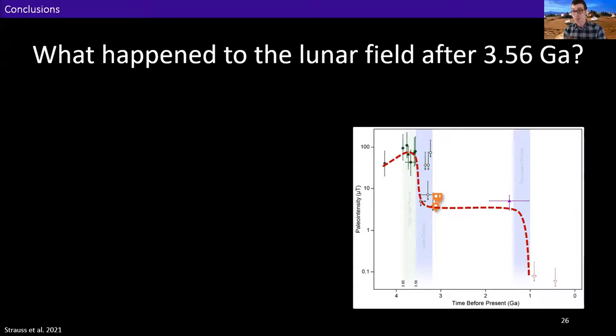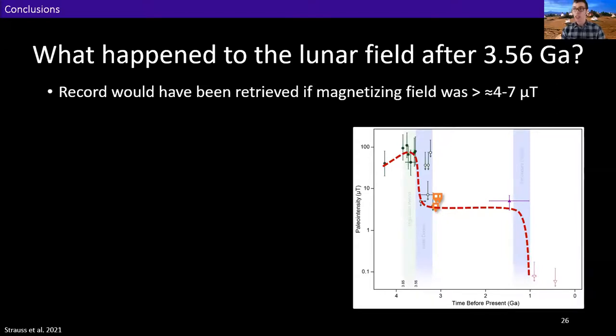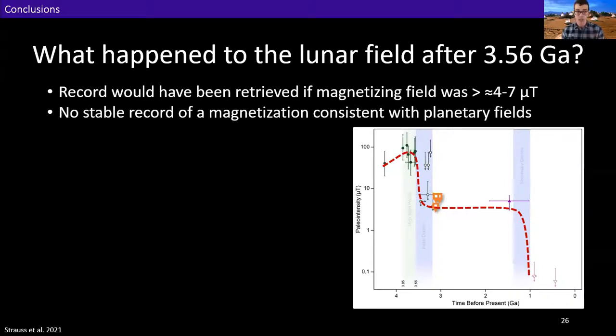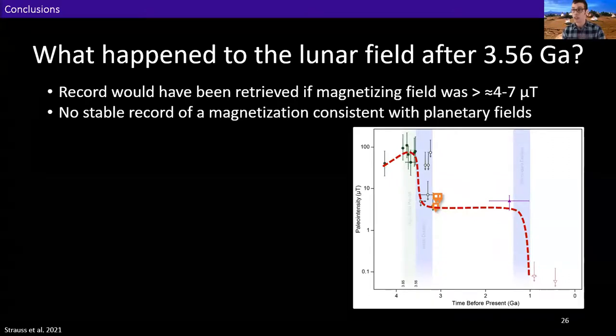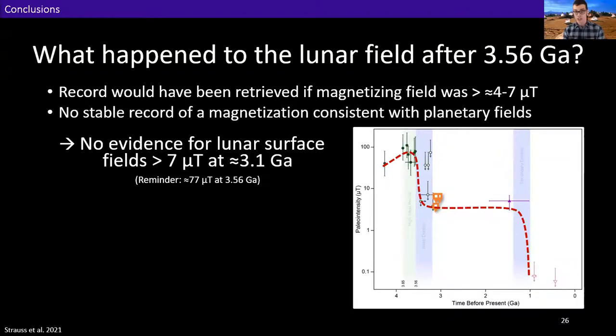Okay, if you zoned out or went to check your phone, I'm now going to summarize my whole talk in about a minute and a half. What happened to the lunar field after 3.56 billion years ago? Our methods would have been able to retrieve a record if the magnetizing field was any stronger than about 4 to 7 microteslas. However, we did not retrieve a stable record of a magnetization consistent with that kind of planetary field. Therefore, we find no evidence for lunar surface fields any stronger than 7 microteslas at about 3.1 billion years ago.